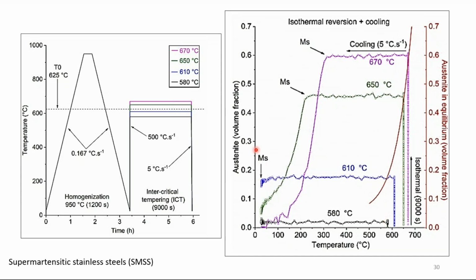However, for the lower temperature below T0, you can see that this equilibrium wasn't reached. That's interesting. So Thermo-Calc couldn't calculate this unstable behavior. But okay, that's one point. The other thing is that you can see that the martensite start temperature changes from case to case, and then we can see a similar phenomenon to the former paper I explained. You can see that even though you produce a lot of austenite during high temperature isothermal treatment, when you go down to room temperature, you are going to stabilize a little amount of this austenite. That's very interesting.